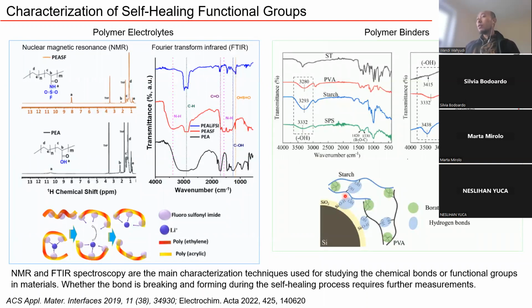And to characterize the self-healing functional groups can also be done precisely by using nuclear magnetic resonance spectroscopy and Fourier transform infrared spectroscopy, as shown by this reference in ACS Applied Materials & Interfaces. The authors use NMR spectroscopy to study the transformation of OH bonds into these functional groups by using proton NMR spectroscopy. Initially, they show a peak at around 10.5 ppm chemical shift of the proton spectra, which corresponds to the OH groups, and then this peak disappears after they change the functional groups into the sulfonyl groups, and then another peak appears at around 8 ppm.